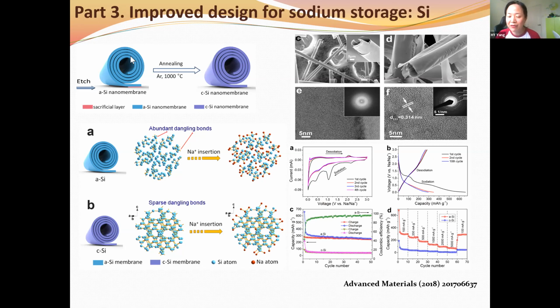And then what we have found out is that we can generate an amorphous silicon membrane structure with a lot of dangling bonds, and those bonds will generate a chemical combination with sodium and bond this sodium to the silicon structure. So the amorphous silicon, in fact, is a very effective material as an anode for sodium-ion battery.